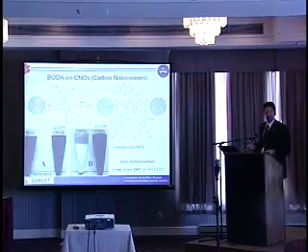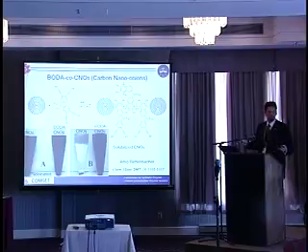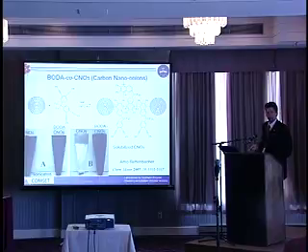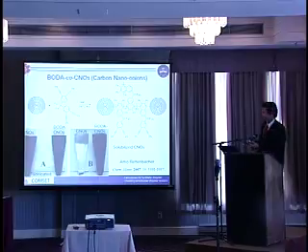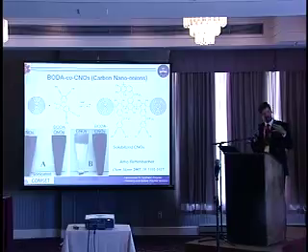The other thing is it's a very reactive group. You can polymerize these things, and it's all radical chemistry, but they're very reactive radicals. And of course, they react with C60. What radical doesn't? But carbon nano onions, which we have an expertise in at Clemson, are normally not very reactive, because these are about 20 layers of concentric buckyballs, and these outer ones are not very reactive because they look like graphite to the radical, which isn't very reactive. You have to have some of that ring strain in order to get that radical to attack.